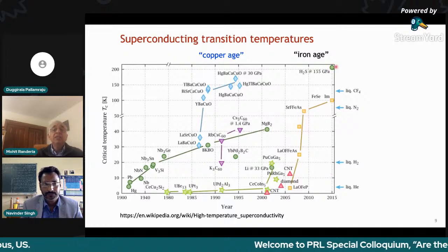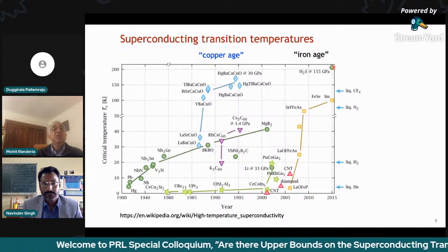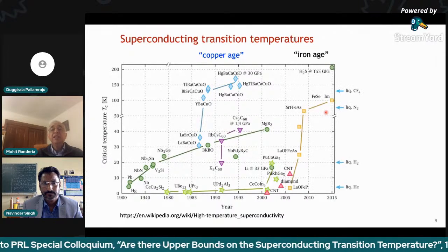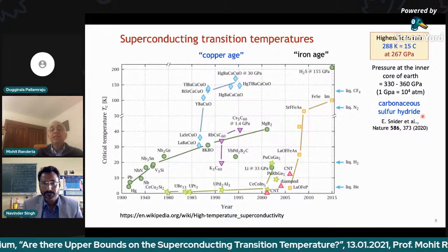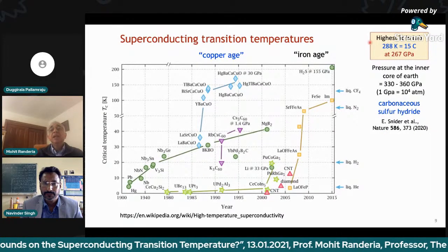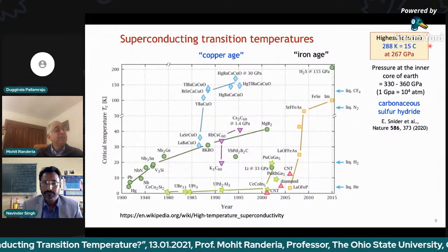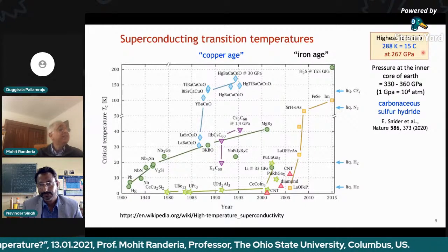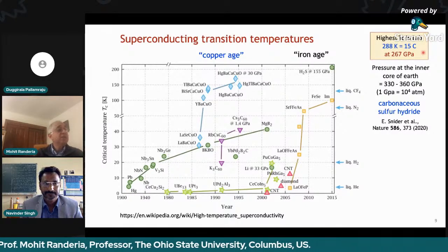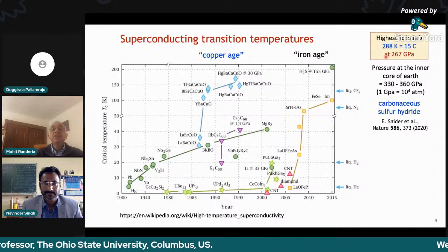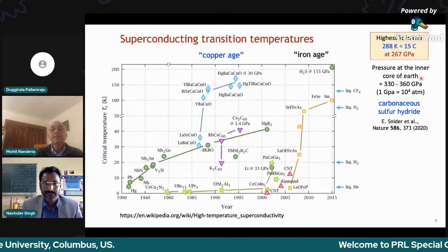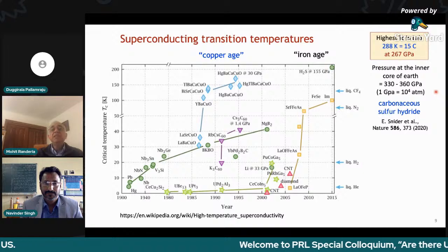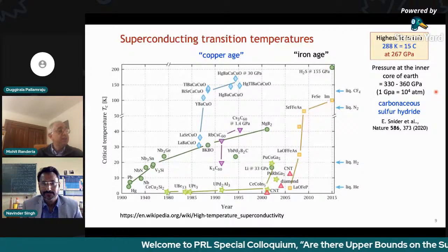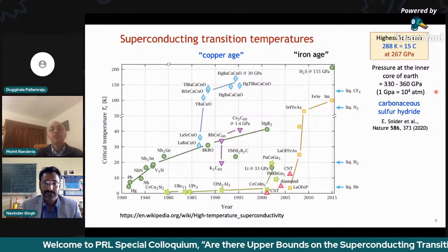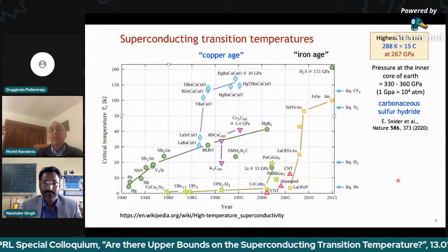And here you can see that there's hydrogen sulfide at high pressures, 150 GPa, which is at 200 Kelvin. And then very recently, just last year in Nature, it was reported that the highest transition temperature seen in a laboratory is 15 Celsius. Okay, so it's a room temperature superconductor. The only downside is it's at a humongous pressure of 260 gigapascals, which is roughly 75% of the pressure at the core of the Earth. Okay, so it's under only very high pressures that this is seen. And this is in carbonaceous sulfur hydride.